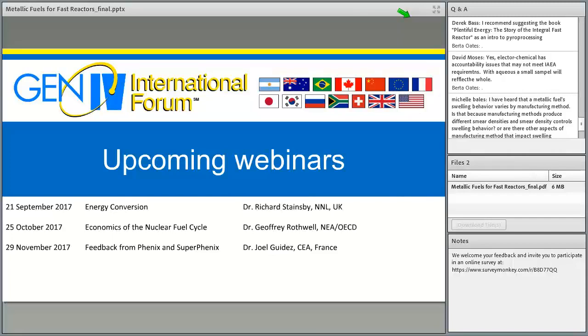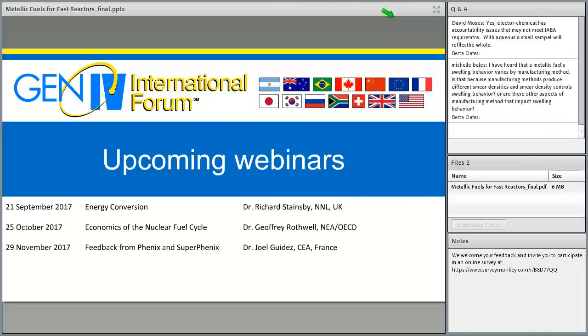Michelle, you're right. That was observed long ago, decades ago. However, most approaches to metallic fuel fabrication today, if you're using a fabrication process, say like extrusion, that would produce a textured microstructure, it's typically always the case that you would then have some post-extrusion annealing process to homogenize the alloy. So as long as you homogenize the alloy prior to irradiation, metallic fuel performance seems to be fairly consistent.